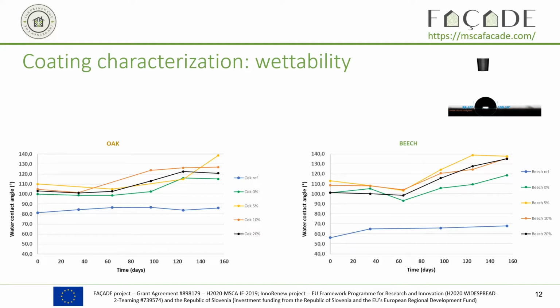This is due to the choice of this tung oil that is reticulating with the ambient oxygen, and that keeps reticulating over time and keeps increasing the hydrophobicity of the surface. When you compare tung oil alone or tung oil with biocarbon inside, the biocarbon increases even more the hydrophobicity of the surface, in both cases, for both wood species.